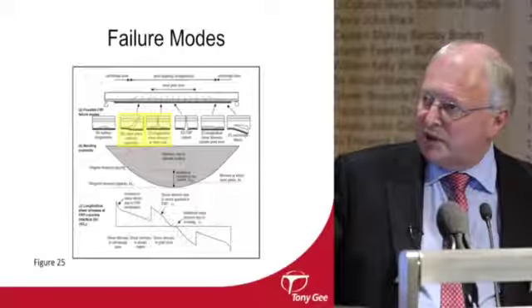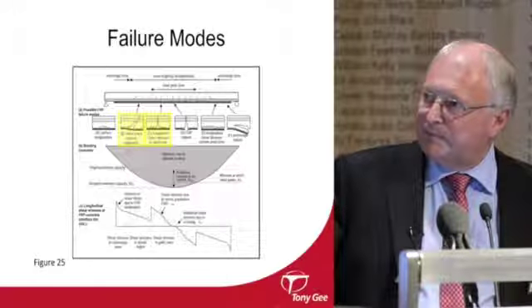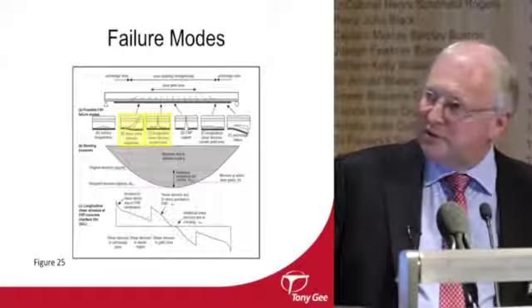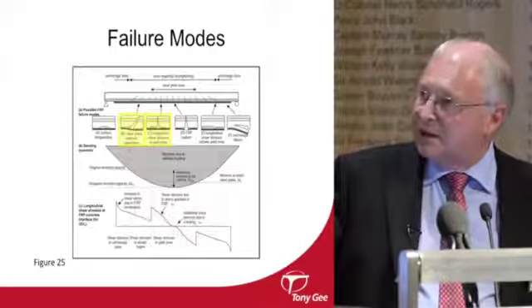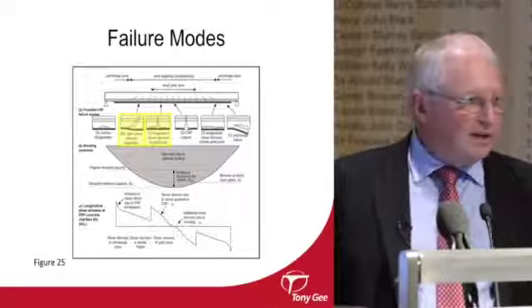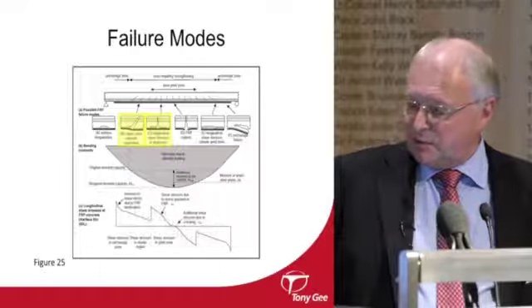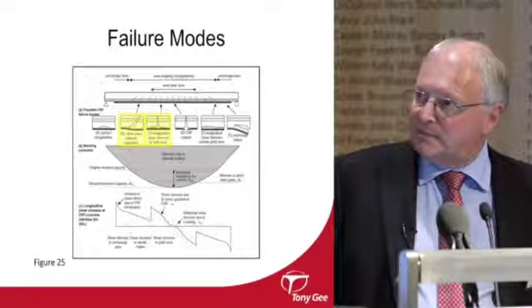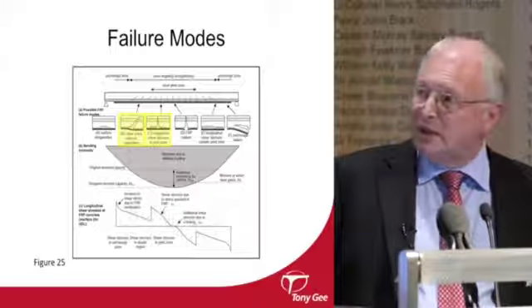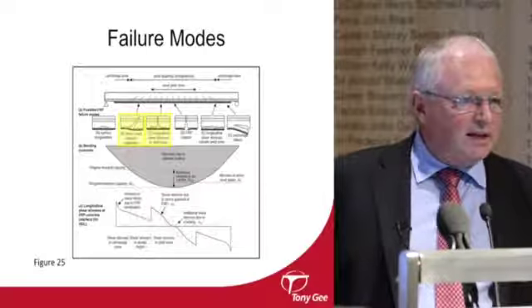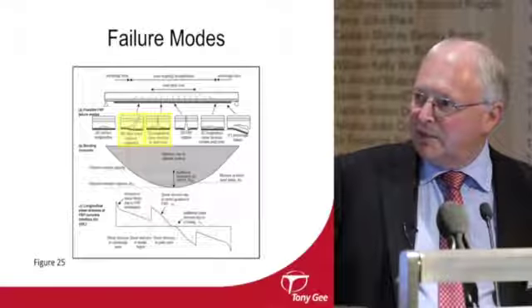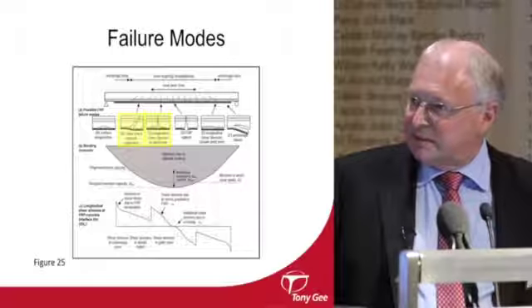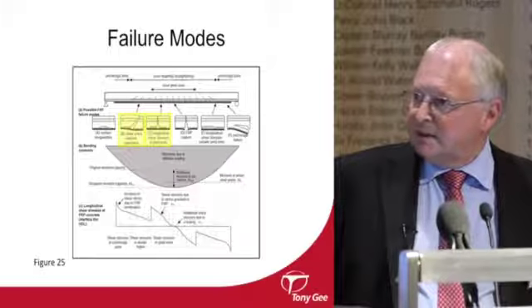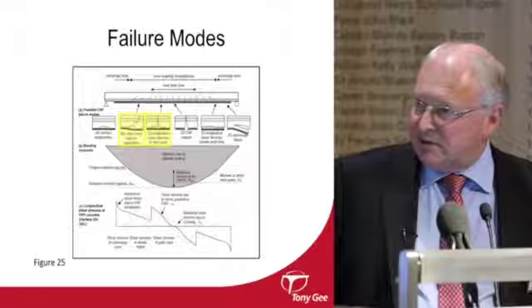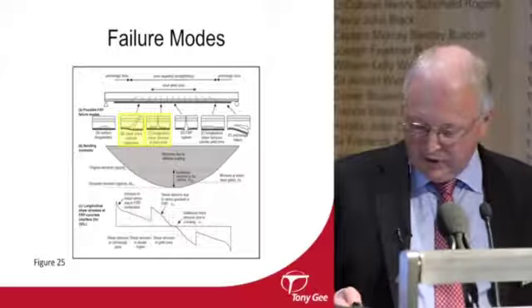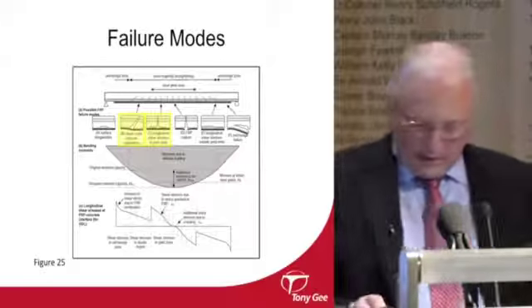The two I'm just going to highlight here. One is shear crack induced separation. So as it says on the can, it's areas where you get high shear, and also longitudinal shear stresses in the yield zone. When the stresses in the steel reinforcement are nearing yield, you then get almost disproportionately high interfacial stresses along the bond line. I won't bore you with the mathematics, but it's expressed in this diagram down here. So that obviously is an area that we need to look at very closely, and TR55 deals with that.